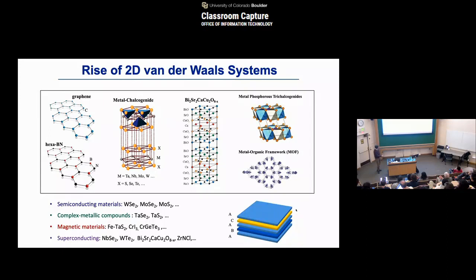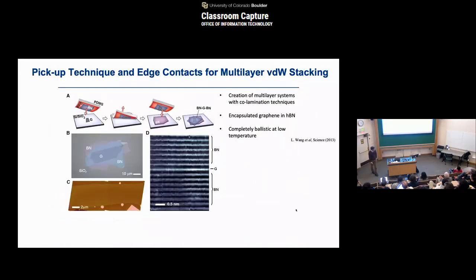And that basically provides us a lot of opportunity to explore interesting quasi-three-dimensional structures. It's not just the PowerPoint demonstration I showed here. Indeed, experimentalists demonstrated one can build this type of heterostructure. In this particular case, it's graphene in between boron nitride, assembled in a rather simple way by successfully picking up crystals cleaved down to monolayers. But nevertheless, at the end of the day, you get very similar quality of heterostructures that one can build by MBE systems.